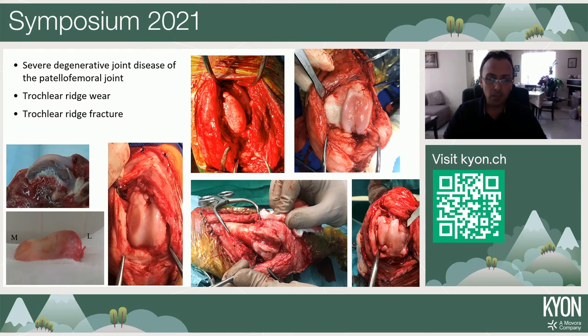As we know, patella luxation is a good model for development of osteoarthritis. So in many cases, we find a trochlea that is completely covered by osteophytes. Because of this massive osteophytosis, there's simply no room for the patella anymore in the trochlea. Sometimes, like the case on the right, you can see a new trochlea formed and covered by almost normal cartilage, contrary to the normal trochlea, which doesn't have much cartilage at all, just a very thin layer, probably a very soft cartilage or like a synovial membrane, covering the subchondral bone.